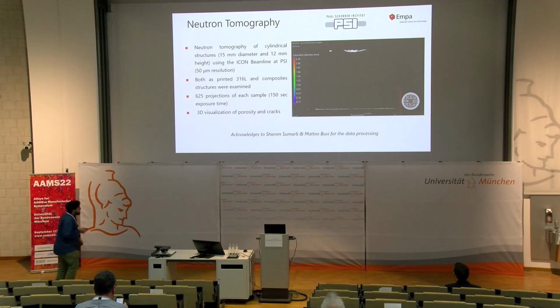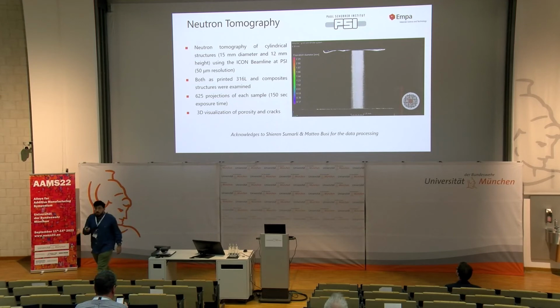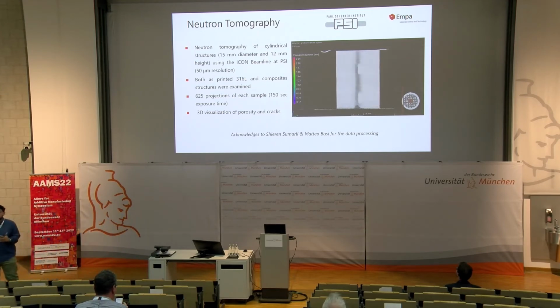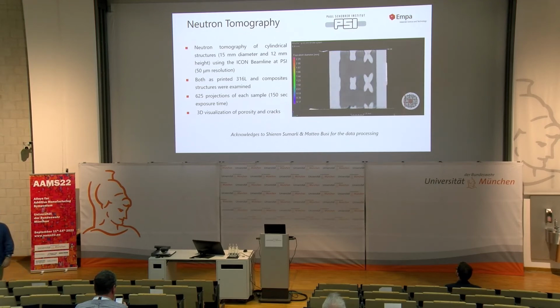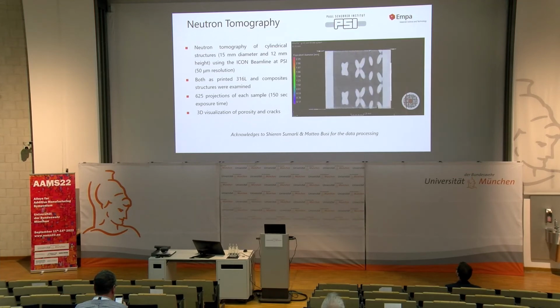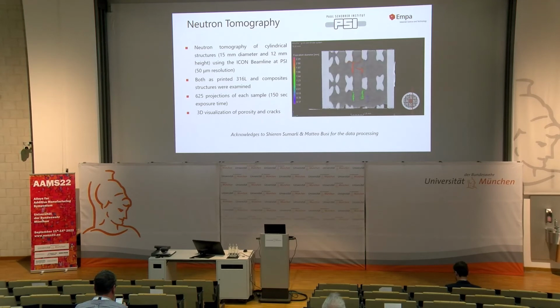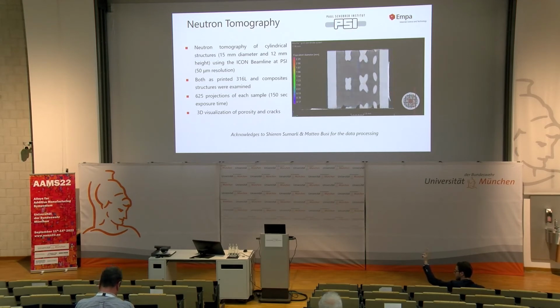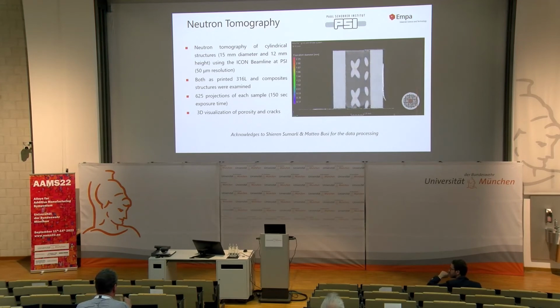The second measurements have been done once again using the ICON beam line. So here we examined the cylindrical structure. Actually, we examined the lower part of the cylindrical structures where we had printed the internal lattices. Due to geometrical restrictions, we cut the sample into two. So each time, we examined a sample having a height of 12 millimeters and a diameter of 15 millimeters. We start by having as a reference the as-printed structure, and then we move on with the cast structures, having 625 projections, for example, and an exposure time of 150 seconds. So the aim here is to have a 3D reconstruction of the sample, emphasizing the formation of porosity and